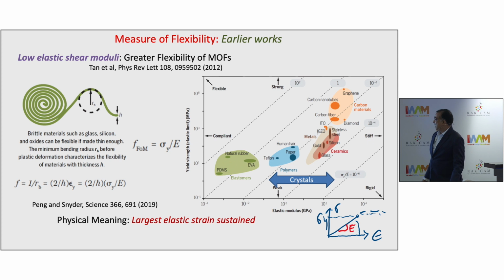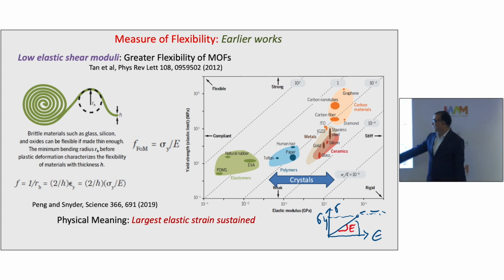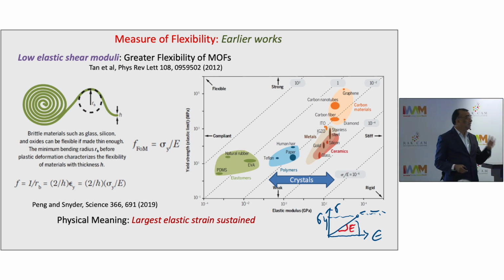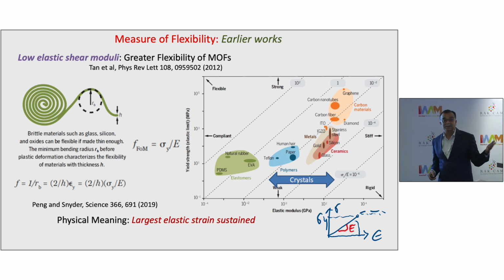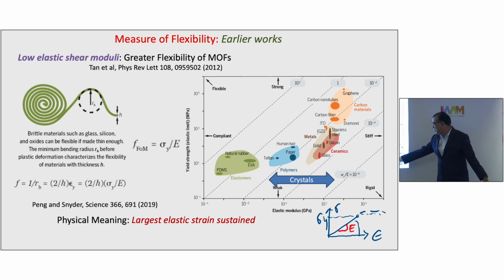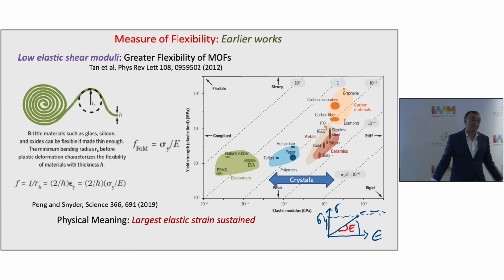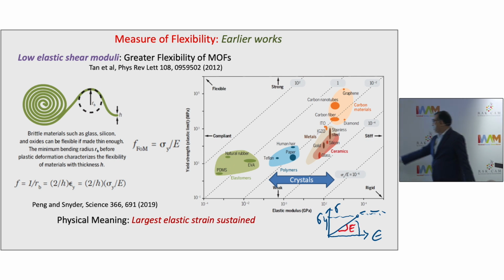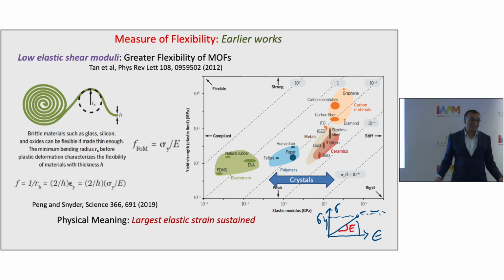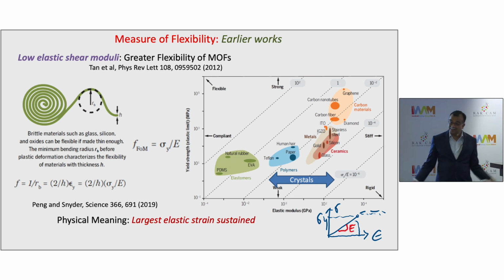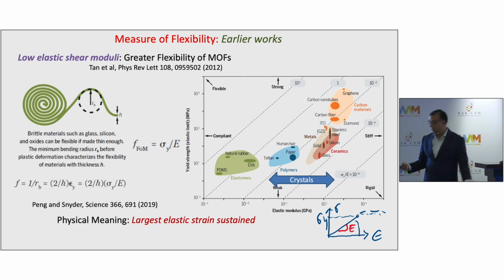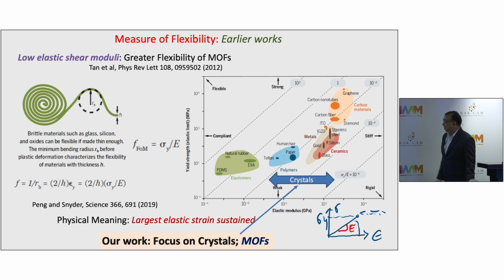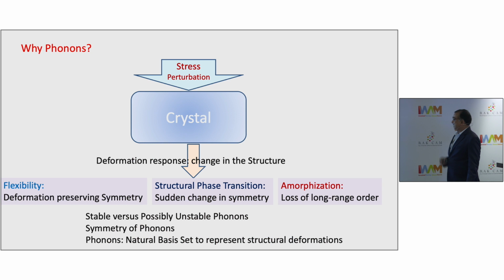So let me move on. Just before I move on, it's possible to physically interpret this figure of merit of flexibility. Sigma y is the yield stress after which the material deforms in a non-linear manner. Okay, so sigma y upon E: E is the slope of this stress by strain curve, and sigma y is where it breaks if it's a brittle material or starts bending. So this ratio basically tells you the largest possible elastic strain a material can accommodate, and that's a reasonably good description of flexibility as well. So what we will be doing is to focus on this window, and let's see where we go.